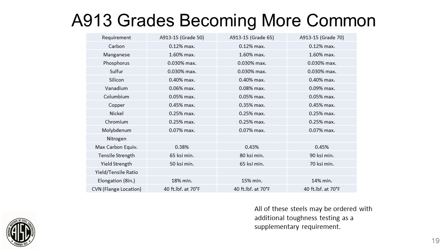And the first thing is you look through the requirements because it's got different grades, 50, 65, 70. But look at that carbon max. You can see a difference right away, right? You've got a 0.12 max versus roughly 0.20 that we saw on the other page. That's significantly lower. The manganese is a little bit higher because the carbon's lower. And then you look, the phos and sulfur are much more restrictive. Silicon's about the same. Vanadium, columbium, the standard grain refiners.